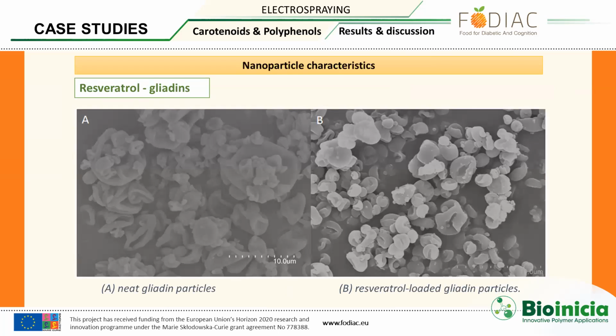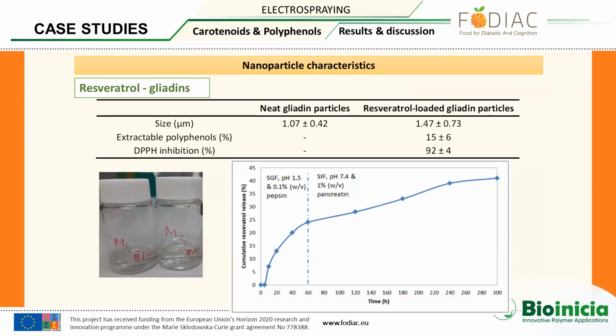Then we have also encapsulated resveratrol in gliadins, and we have obtained raisin-like particles. This is common for alcohol-based encapsulating materials. We have observed that the size of the particles is in the range of the micron, with a high encapsulation efficiency, and the resveratrol maintains its antioxidant activity. The particles were not soluble in water and remained stable for a long period. And we have also studied the release of the particles in simulated gastric conditions.